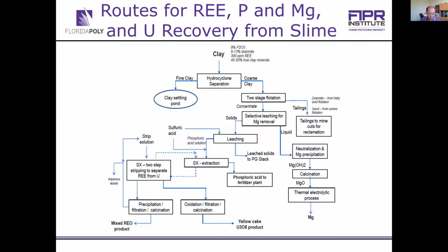Then the underflow from the hydrocyclone goes through a flotation process to further concentrate phosphorus and rare earth elements into a concentrate. Then we use a stage-wise leaching process. First, there's low acid, like 3.5 pH, to remove the magnesium and recover it as a product, either as a pure magnesium or magnesium oxide product. After removing the magnesium, the phosphate rock goes through a stage-wise leaching process so we can recover the rare earth elements and the phosphoric acid product. In this way, we call it comprehensive recovery of all the valuable elements from this waste product.